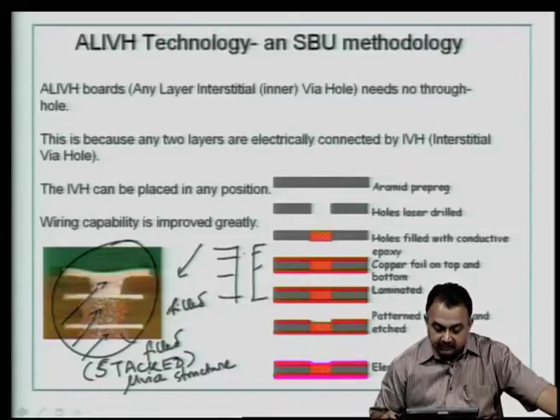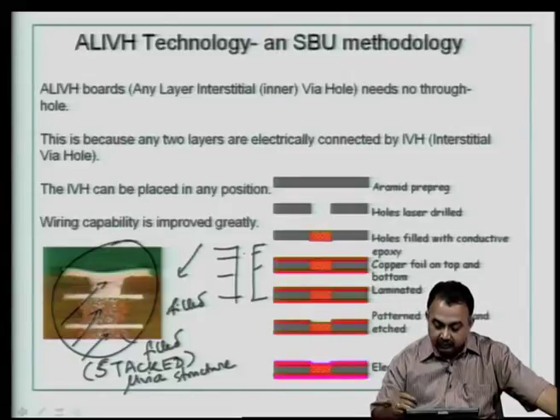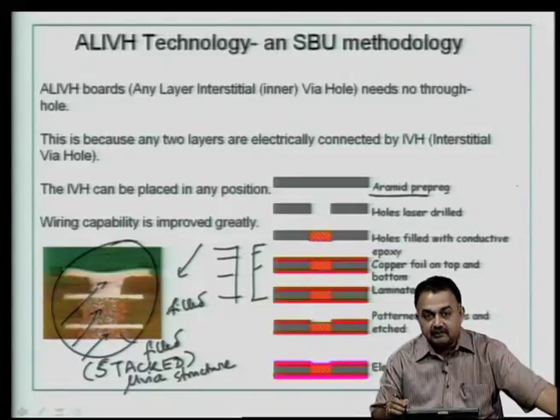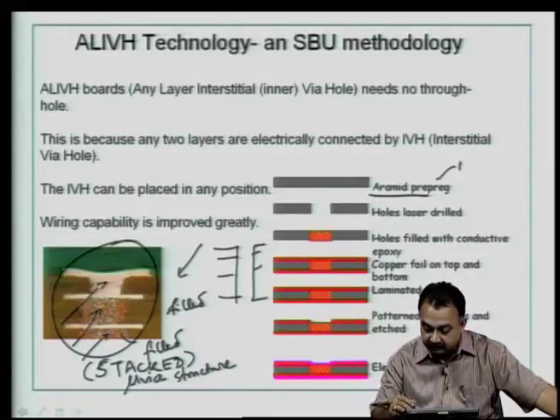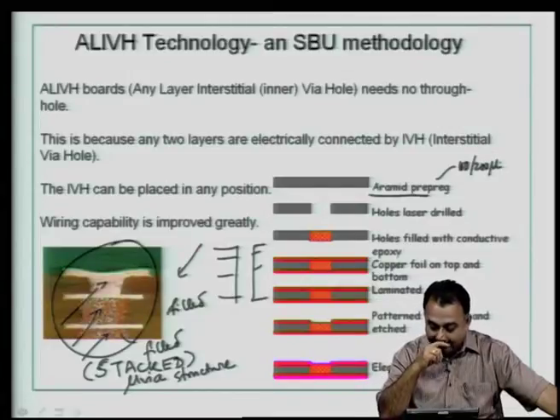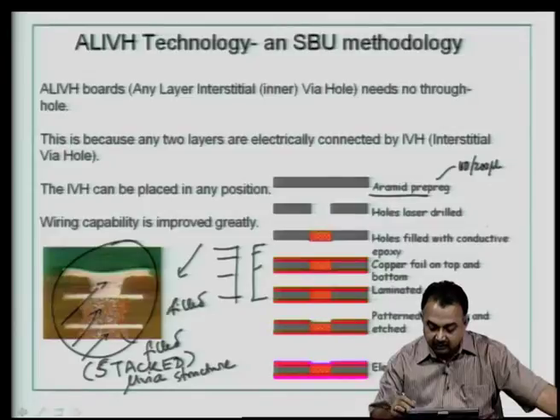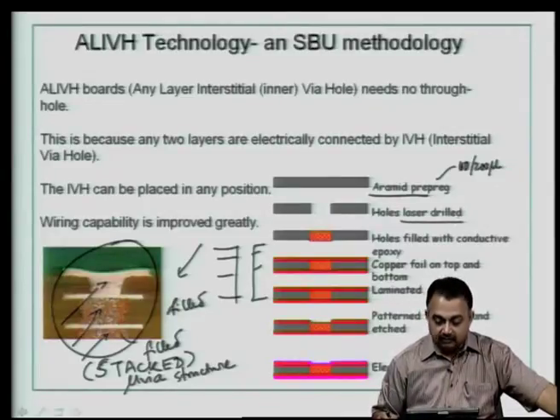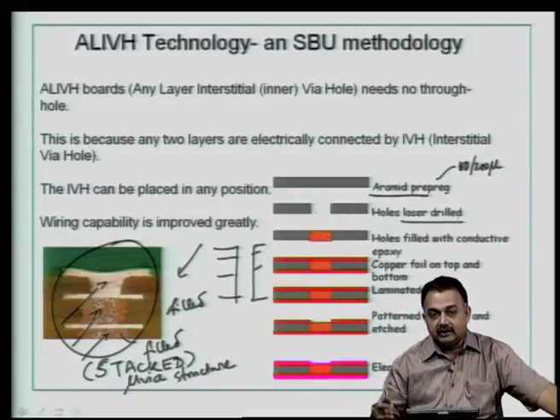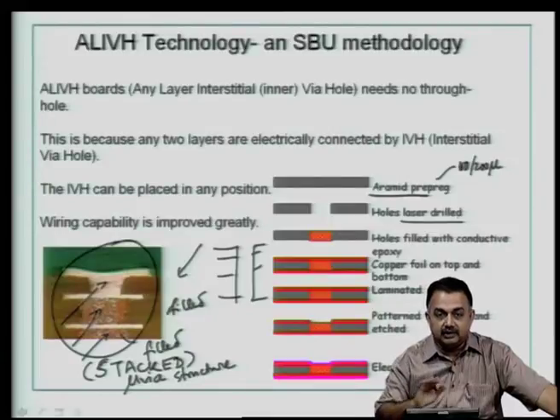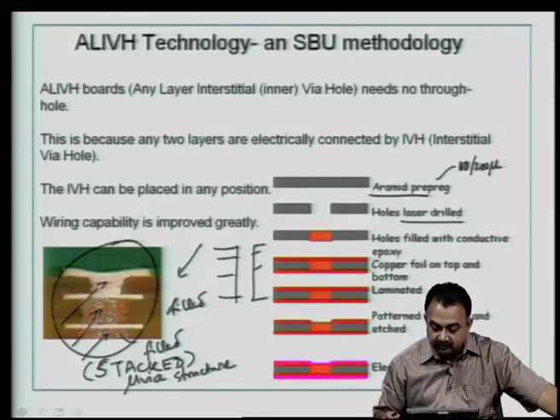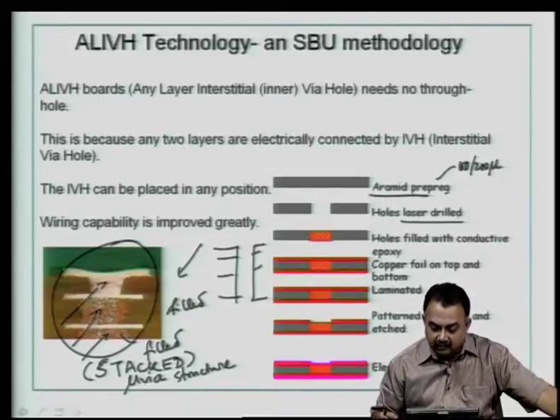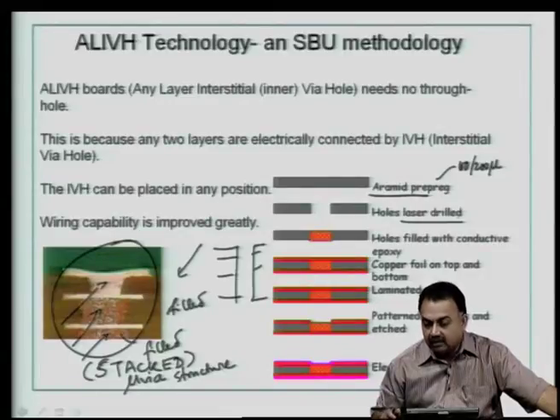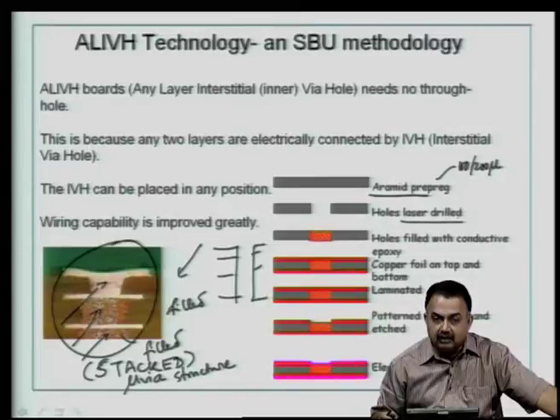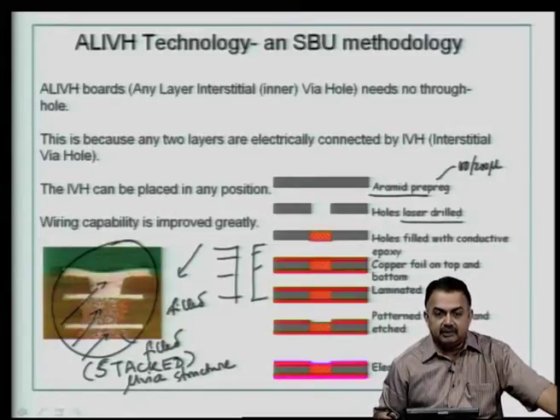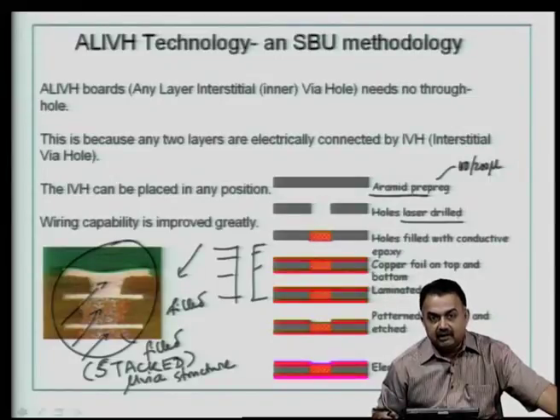So, how do you prepare this kind of board using ALIVH? Use a material called aramid fiber, and the prepreg is made out of the aramid prepreg. Let us say this is typically about 100 micron or 200 micron. Now, you can use this as a substrate and do laser drilling based on your CAD data. First, you create the holes. So, you feed it into your laser drilling machine and you get a substrate that has been generated with the microvia structures. Now, using a stencil printing process, because you need to use the right conductive epoxy material. Instead of epoxy you can use some other material, but the general commercial, economic friendly material is epoxy resin.